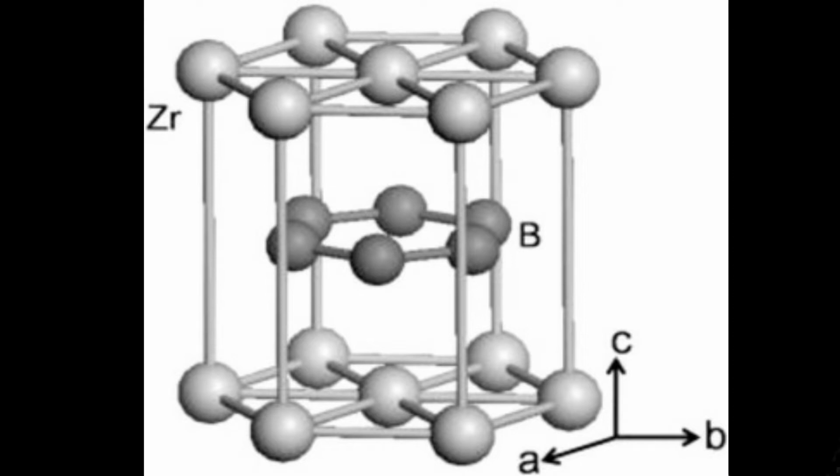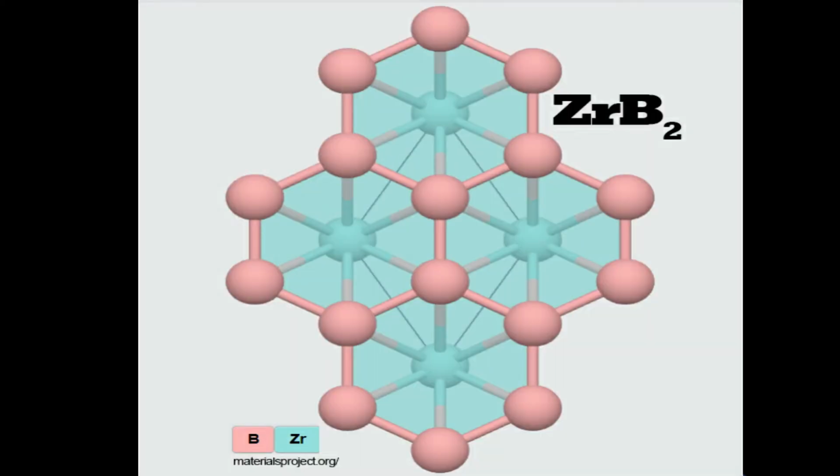It stated that the study has shown that the thermal expansion of zirconium diboride is anisotropic, which means that it has a different thermal expansion property along the various lattice directions. Because of its anisotropic properties, it has varying bond strengths that determine the stiffness, thus the expansion of the material.